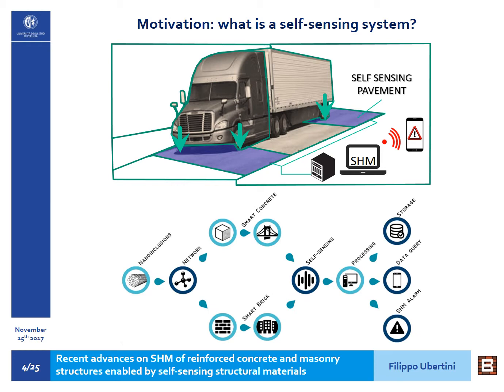So in this research we achieved this smart property into concrete and clay bricks by doping these construction materials with electrically conductive nano-inclusions. In particular, we'll see carbon nanotubes that create conductive networks inside the materials in such a way that the materials themselves become conductors.